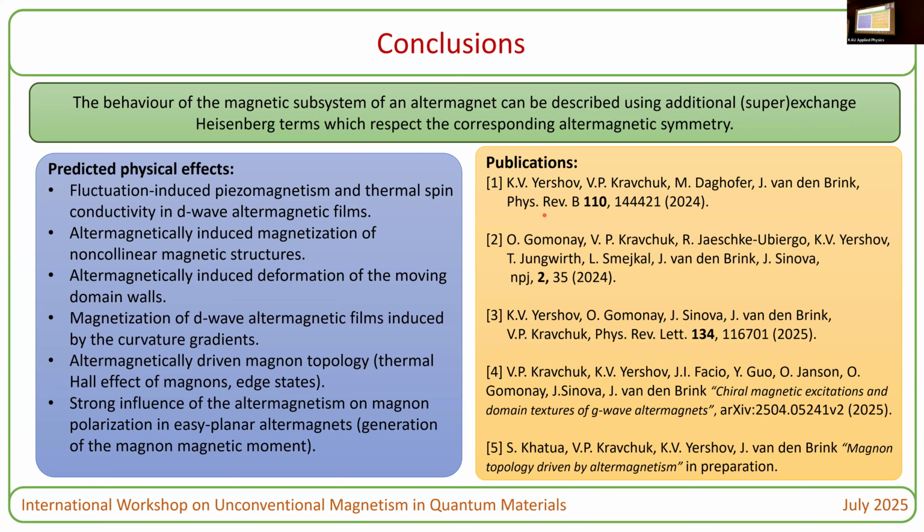Okay, go ahead. There's a question here. Volodya, this is Sergey. I would like to ask the following question. You mentioned that spin conductivity depends on temperature. Are you talking about the spin-Seebeck effect? This is more like the Nernst effect. I mean, we have the spin current in response to a temperature gradient. However, in contrast to the Nernst effect, this current not necessarily flows perpendicularly to the gradient. It can flow in different directions depending on how this gradient is applied with respect to the crystallographic axis.